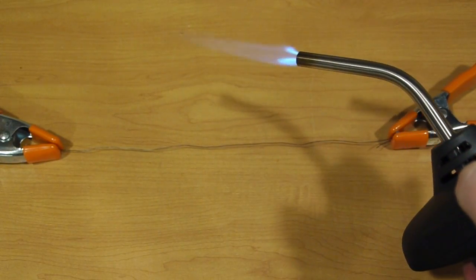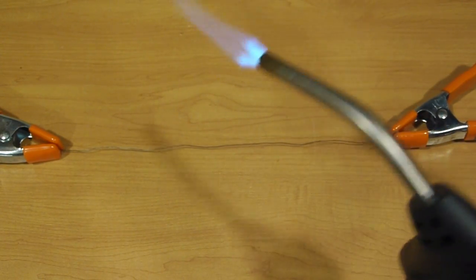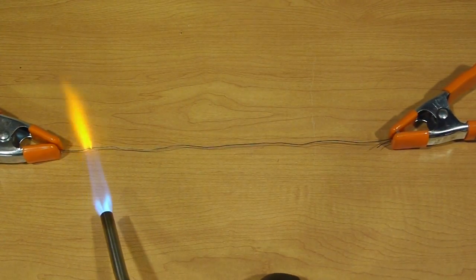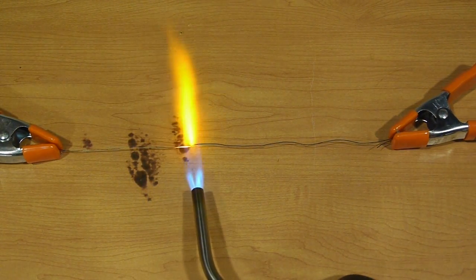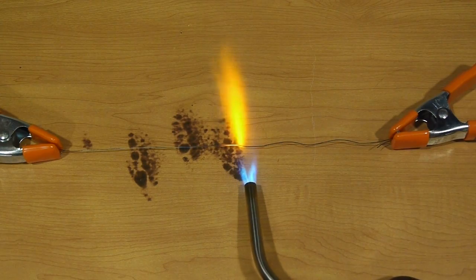Now here's where the magic happens. When we apply 600 degrees Celsius to the wire itself, we bake it into whatever position it is stuck in. In this case, I'm just straightening the wire out from a coil.